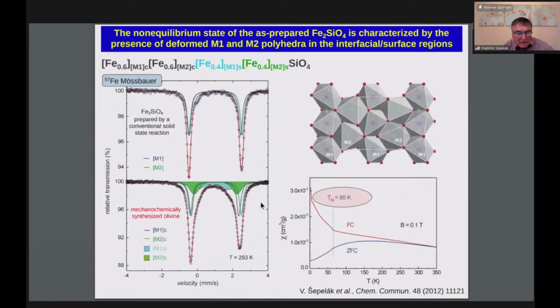If we look at the Mössbauer spectrum of this mechanochemically synthesized olivine and compare this spectrum to that of bulk material, we see 2 spectral components in the case of conventionally prepared matter corresponding to ferrous ions on M1 and M2 sublattices. And the Mössbauer spectrum of mechanosynthesized material was fitted with 4 subspectra corresponding to 2 subspectra with the same parameters corresponding to the core of nanoparticles, and 2 additional subspectra corresponding to ferrous ion in the shell.